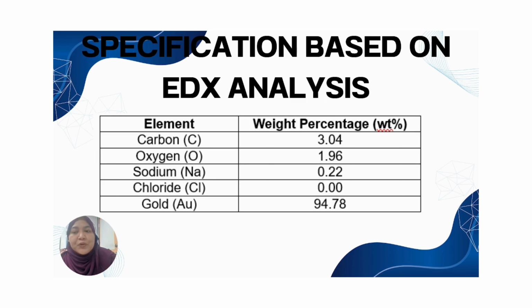Here is the elemental composition of the synthesized AuNPs as analyzed using EDX. This table presents the elemental composition of the synthesized AuNPs based on EDX analysis. As shown, the dominant element is gold with a weight percentage of 94.78%, which strongly suggests that the synthesis was successful. Minor elements such as carbon, oxygen, and trace sodium were also detected, likely from residual reagent during synthesis. Notably, chloride was not detected, which aligned with our expectation post-synthesis and purification.